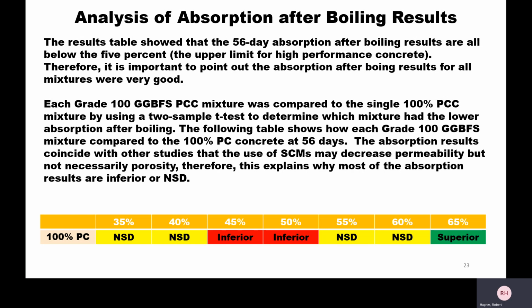So, a statistical analysis of absorption after boiling. The results table showed that the 56-day absorption after boiling results are below the 5%, which is the upper limit for high performance concrete. Therefore, it's important to point out that the absorption after boiling results for all mixtures were very good. Each grade 100 GGBFS mix was compared to the control by using a two-sample t-test to determine which mix had the lower absorption after boiling. The following table shows how each grade 100 GGBFS mix compared to the control at 56 days. The absorption results coincide with other studies that the use of SCMs may decrease permeability, but not necessarily porosity, like I was saying earlier. So this explains why most of the absorption results are either inferior or not statistically different.